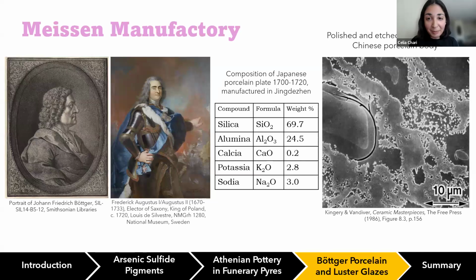But on a lighter note, it's really interesting from a ceramics perspective to compare the composition of porcelain from the Far East to that of Europe. It's quite intelligent what Böttger and Schirnhaus ended up doing. So to create the porcelain bodies, Chinese craftsmen mixed white kaolin clay with finely ground China stone as their temper. And during these high temperature firings, the mineral components of China stone reacted with kaolinite to form a viscous liquid phase, which became a glassy solid upon cooling.